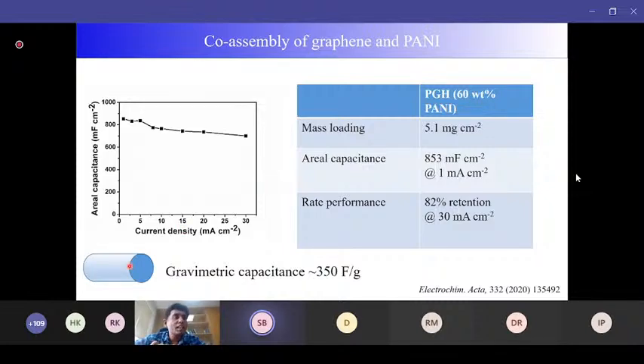So this is a schematic of the polyaniline nanowire. All the Faradaic reactions happen on the surface. If you go to the bulk core of these nanowires, they are effectively unutilized. So although we have used polyaniline nanowires, mostly their surface is active, but the core is inactive. So we can remove the core. This is one possibility, or we can downsize this nanowire to a more nanoscopic scale, like 30 nanometer or 20 nanometer, so that there will be less core structure, mostly surfaces.